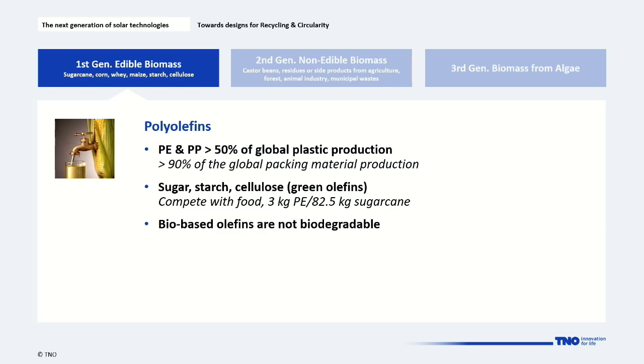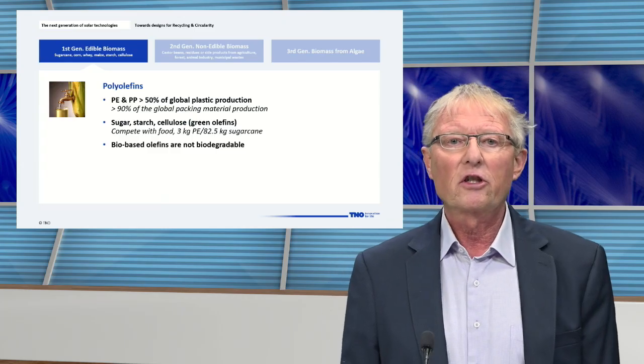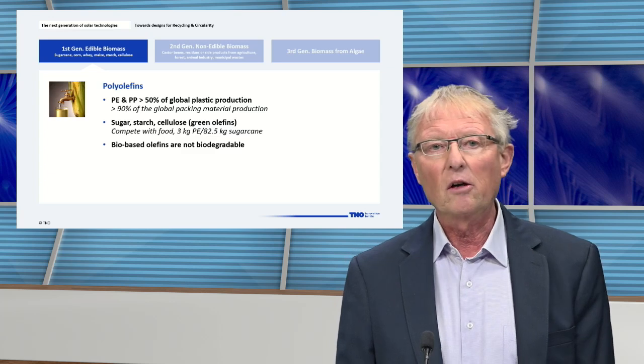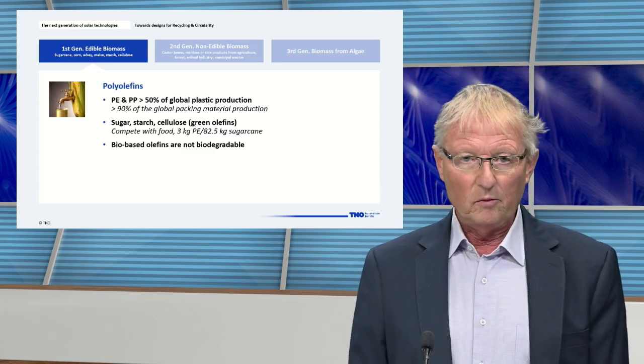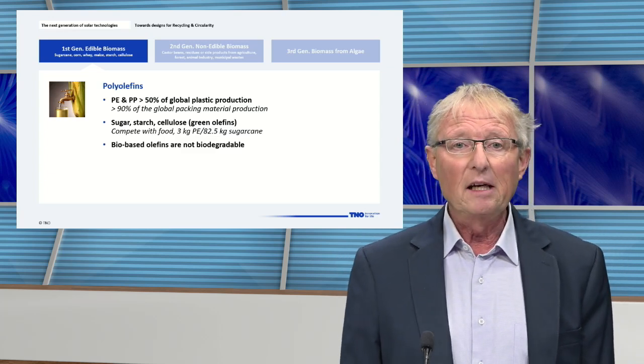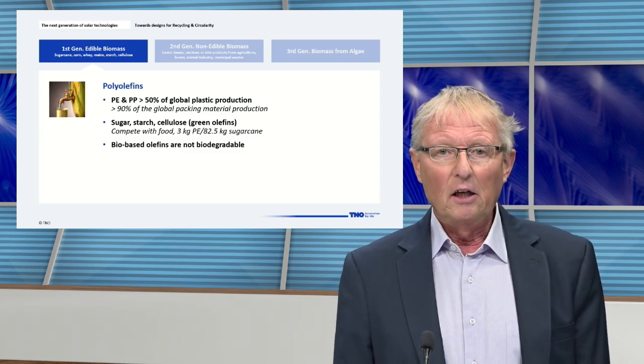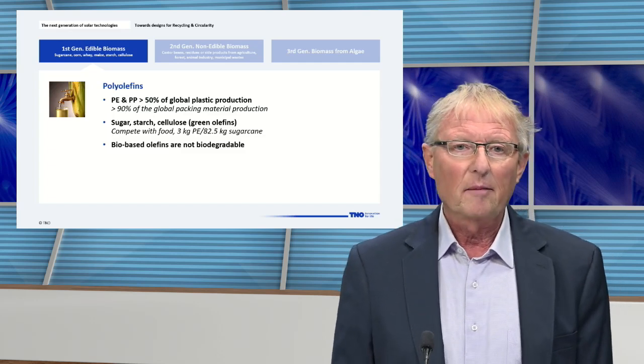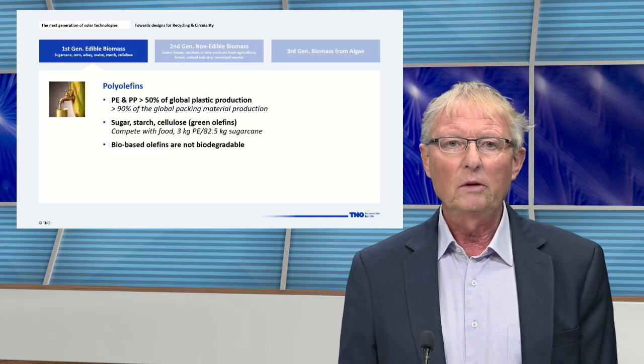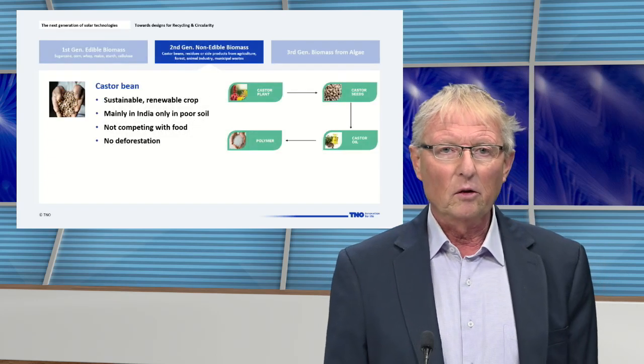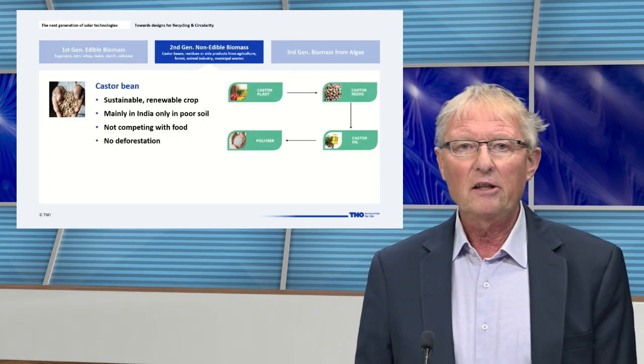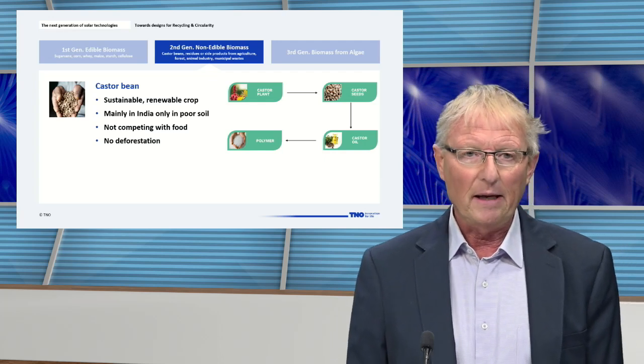So if you take a look at the advanced biocircular materials, we can make these polyolefins from sugar, starch, celluloses. It's called the green olefin, but it competes with food. So 3 kilograms of polyethylene would require 83 kilograms of sugarcane. So that's a no-no. And therefore, we better go to check the second generation, which is the non-edible biomass.